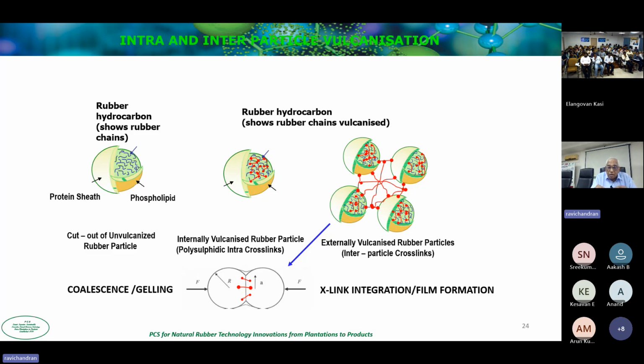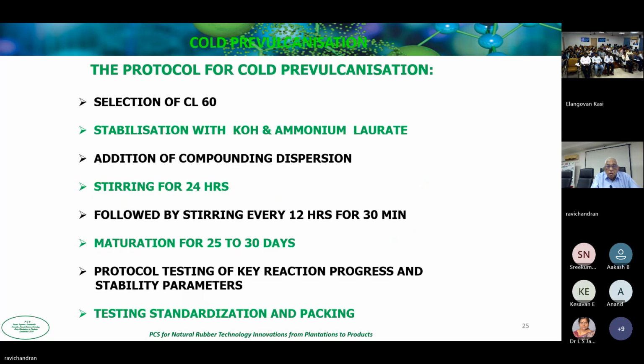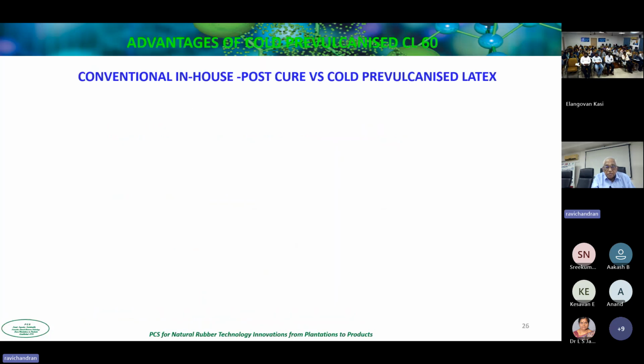And then when we coalesce and gel it, the droplets will all coalesce together and form a film. So you can make very thin films of 0.02, 0.023, very thin films to very thick films. So this is the protocol we follow for pre-vulcanization: selection, stabilization, addition of dispersion, stirring for 24 hours, stirring for 12 hours, for 30 minutes, maturation for 25 to 30 days, testing of key reaction progress and stability parameters, testing and standardization.